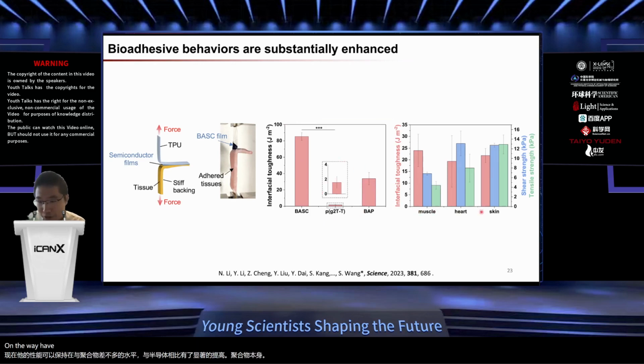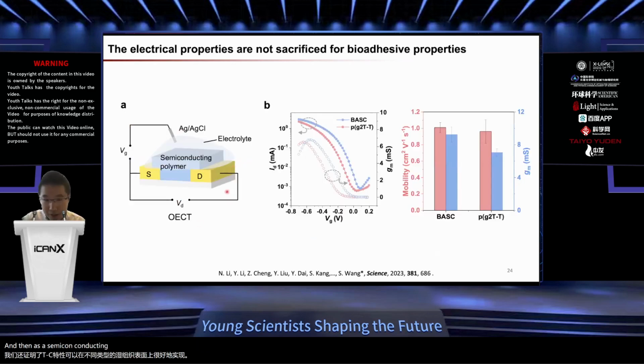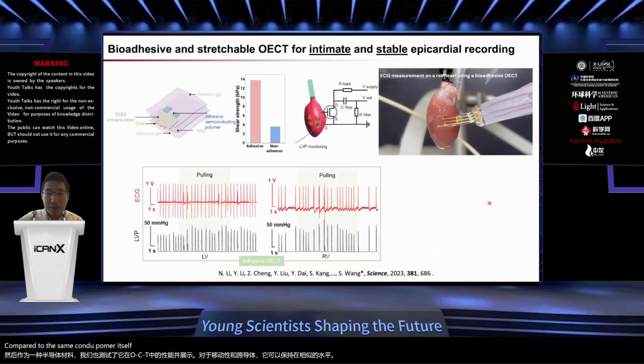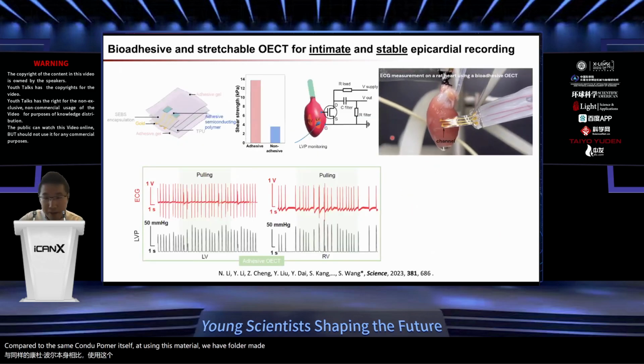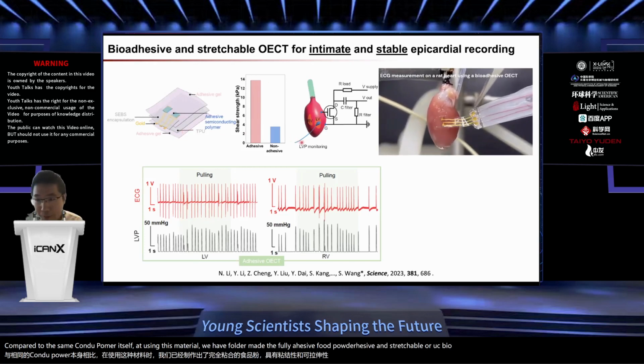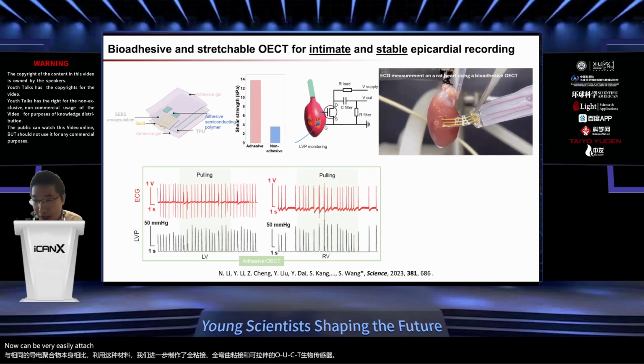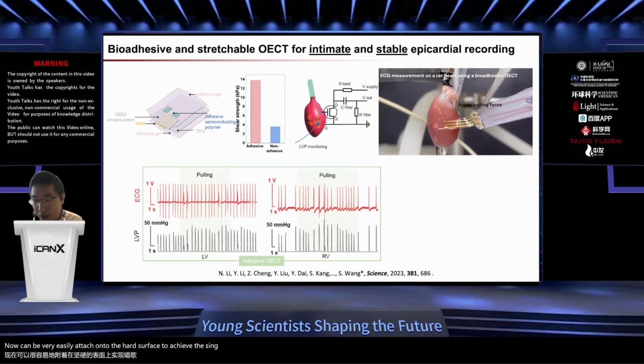We have also shown that the adhesive property can be well achieved on different kinds of wet tissue surfaces. And as a semiconducting material, we also tested its performance in OECT and showed that for both the mobility and the transconductance, it can maintain a similar level compared to the semiconducting polymer itself. Using this material, we have further made a fully bioadhesive and stretchable OECT biosensor that can be very easily attached onto the heart surface to achieve the sensing function by just a simple, gentle pressing.